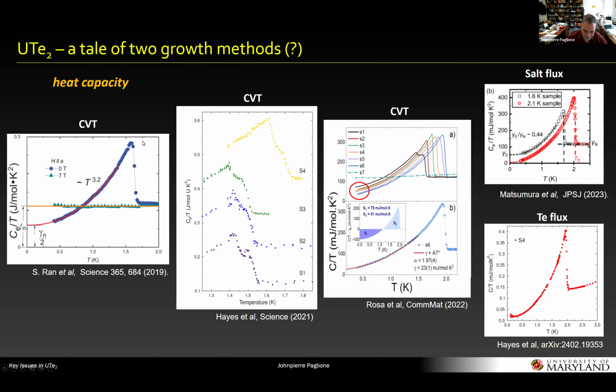In hindsight, the first observations we made of the specific heat transition alerted us to the fact that there was this huge residual component of the heat capacity, which in early versions of the paper we actually labeled as gamma over 2, because we were very excited thinking this might be the long sought polarized helium 3 phase. But we quickly realized by doing thermal transport that there were no itinerant states down there. So that didn't seem to make sense.